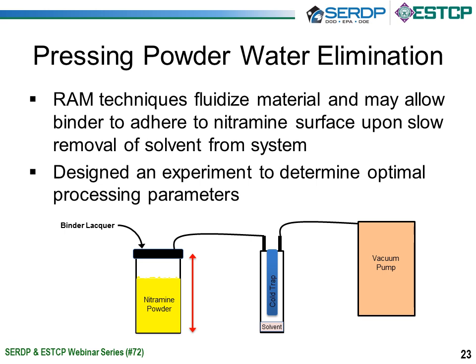As I said, we are trying to develop a methodology for producing pressing powders without the use of water. We're using this resonant acoustic mixing technology to basically fluidize our nitramine powder. We have a mixing vessel where we add our nitramine powder. We take our binder lacquer, we pour it in on top, and then the RAM fluidizes the material and allows that binder to adhere to the nitramine, and then an application of a vacuum will slowly remove the solvent from the system and allow the thermoplastic binder to adhere to the nitramine and form those granules.